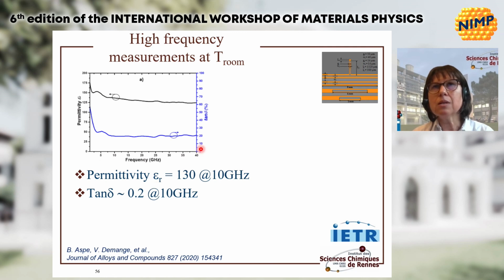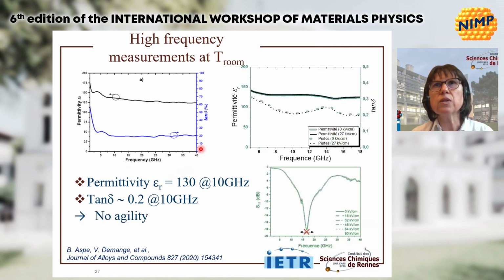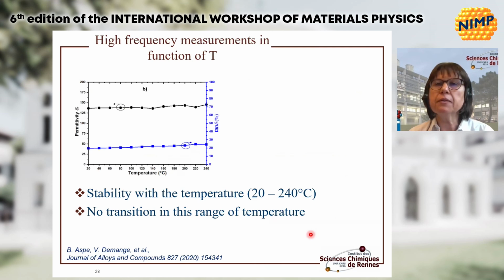What about the possibility to obtain or to see ferroelectricity? Tunability? No tunability, unfortunately. Here we can see some measurements with application of different voltages, and there is no tunability. In temperature, what happens? Between 20 and 240 degrees, there is also no transition in this range of temperature. But we can see that the permittivity is more or less stable, like the losses.